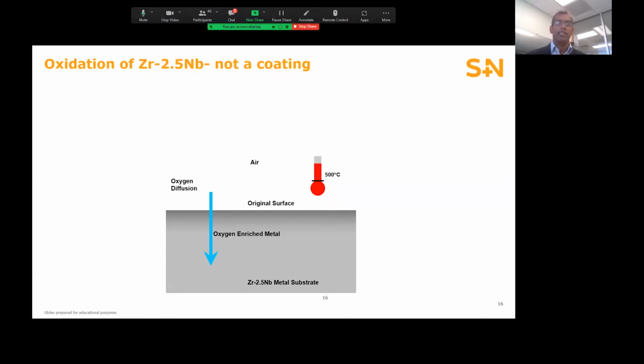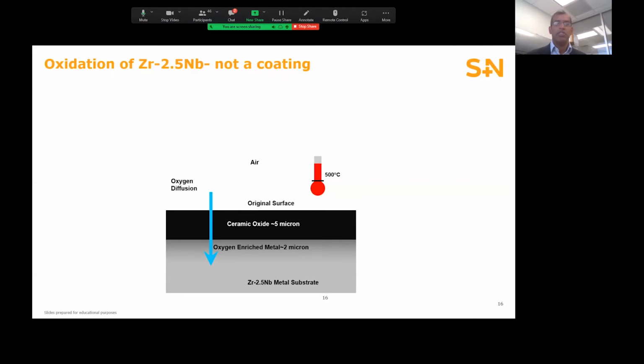At the end of the process, there's an approximately 5 micron thick oxide, below which you have about a 2 micron oxygen enriched zone or diffusion hardened zone. So the ultimate depth of hardening is about 7 microns. And the benefit of this type of material is you have all the positives of a ceramic surface while retaining the fracture toughness of a metal.